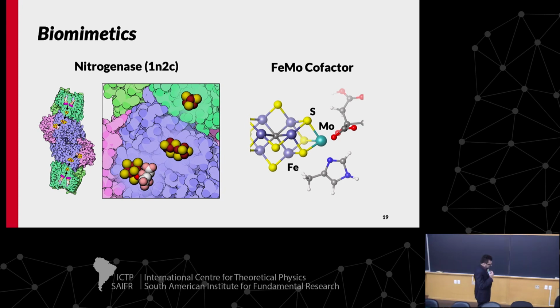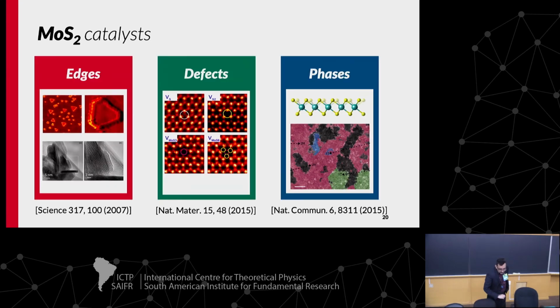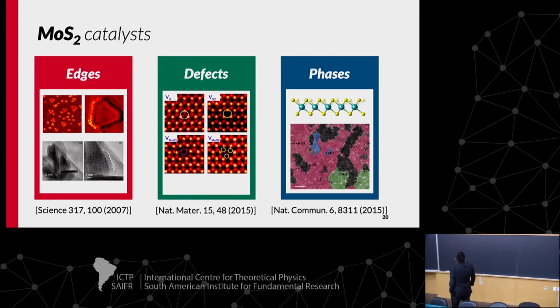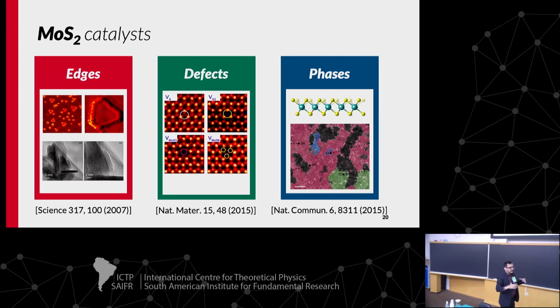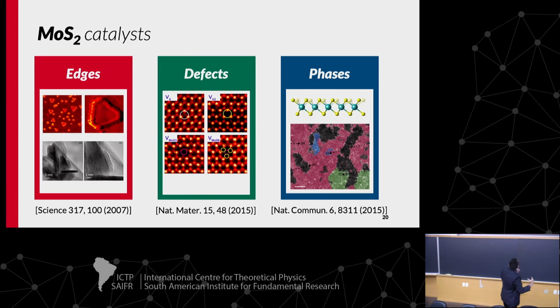this protein to produce hydrogen, and the people looked at this and thought, oh, this is similar to the edge of MoS2, a two-dimensional material. So they proposed a material like MoS2, a 2D material, and use the edges of this material to produce hydrogen. And we see with different sizes of these nanoparticles, the catalysis is scaling with the length of these particles.